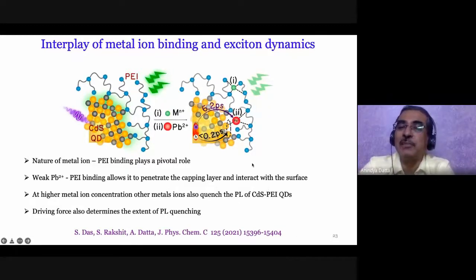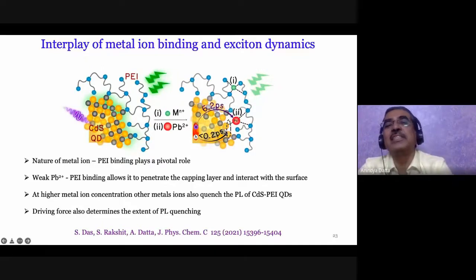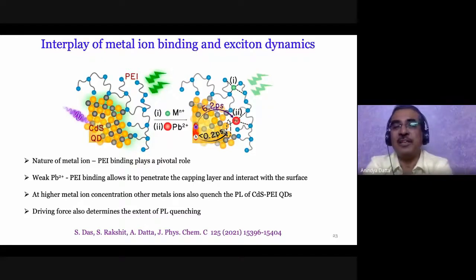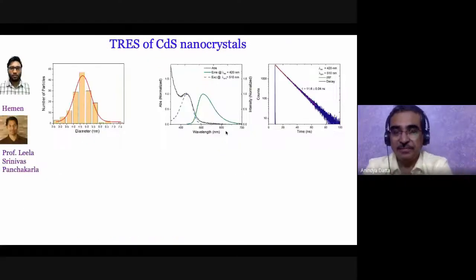So it actually finds its way to the surface, and we figured out that there is an ultra-fast hole transfer followed by an electron transfer that causes the photoluminescence quenching. So the specificity is because of ground state chemistry, that PEI does not like to bind lead, and the excited state process that is taking place here is not just electron transfer, it is preceded by a very efficient hole transfer.